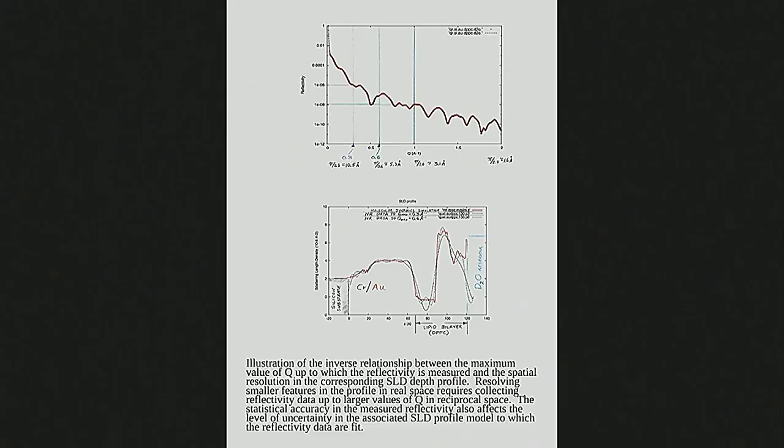Okay, so let's look at a little bit about numbers. What can you really measure? What are the length scales that we're really sensitive to? So here's a real reflectivity curve. This is for this system here. Again, the perpendicular to the film is along the horizontal axis here. So on your left, all the way over here, is a block of perfect single crystal silicon that the beam comes in through with almost zero attenuation. And then there's a chromium layer followed by a gold film of about, I guess this one turns out to be 50 angstroms thick or so.